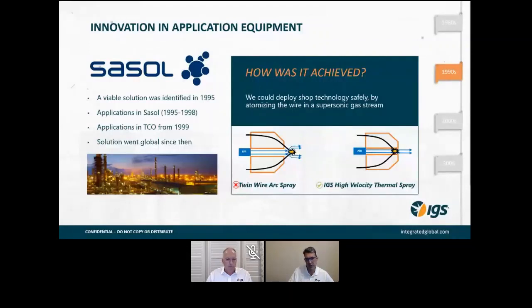So the system was used commercially. Sasol was the first adopter. It was used commercially at Sasol from 1995 to 1998. And the IGS story continues in that in around 1998, this small technology company in South Africa was purchased by IGS. And that's really where the global adoption of the technology started. Chevron was our first global customer for the technology. So in 1999, Chevron was looking for a solution for some challenging materials problems that they were experiencing at the Tengiz Chevroil facility. And February 2000 was when this high velocity thermal spray alloy cladding technology was first used at Tengiz Chevroil.